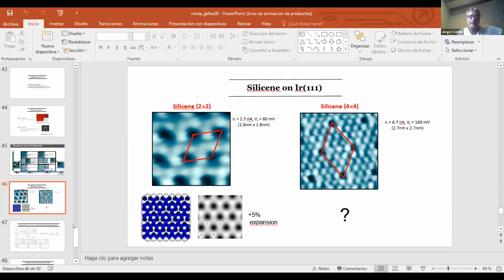all the 3 phases we've shown here, which we believe are pure silicon, I think that the excellent agreement that we achieved, and also the fact that they totally coincide with the optimum DFT energies, is strong evidence that we're hitting the correct phases. As I said, there's another phase that we didn't even grow, about which there's been a debate on whether there's some incorporation of silver. But these 3 phases we really think are pure just because of the good agreement. Everything matches so well that I think this is very strong evidence.